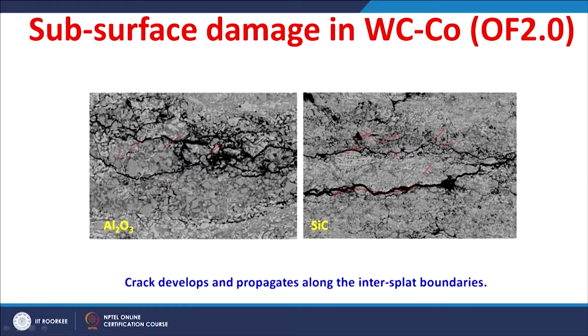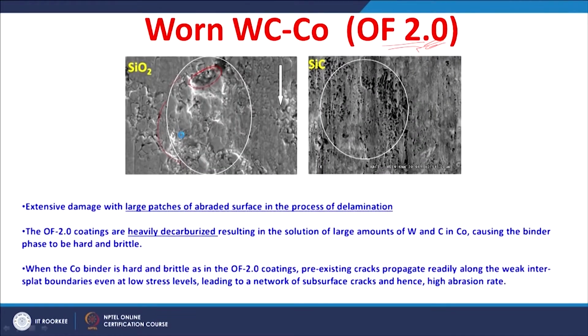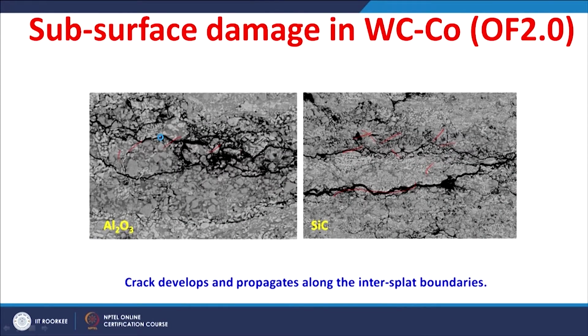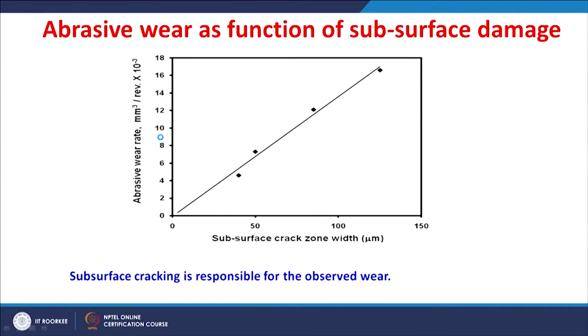So, intersplat boundaries are the stress concentrators. So, even at low levels of external stress, there is a large amount of cracking possible along these boundaries, and that then leads to networking of the subsurface cracks and removing the material from the surface to a larger extent. So, these subsurface cracks and the resultant damage can also be understood with respect to the subsurface crack zone width and the abrasion wear rate behavior.